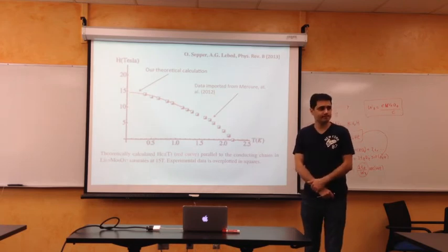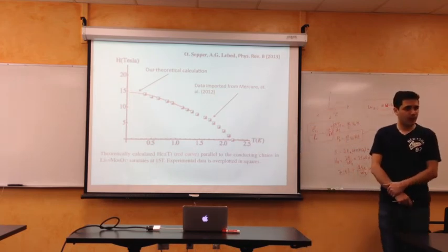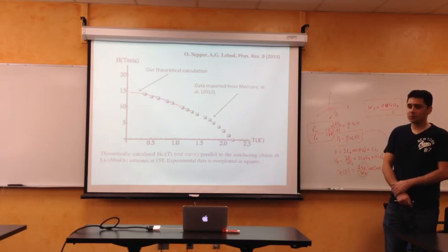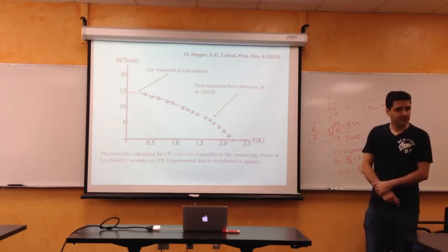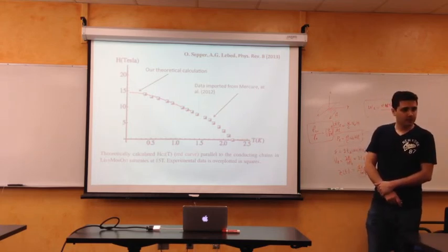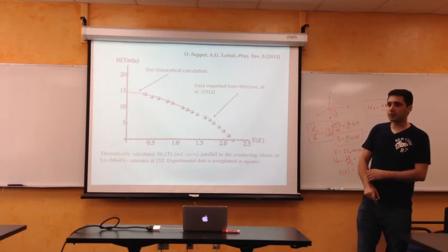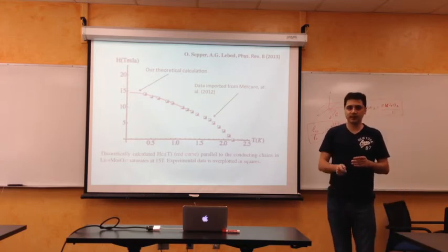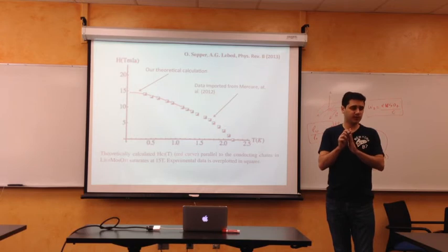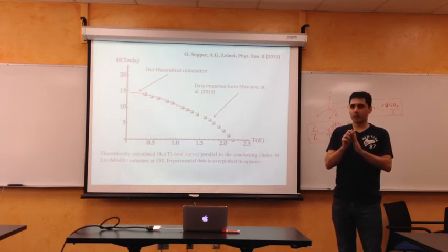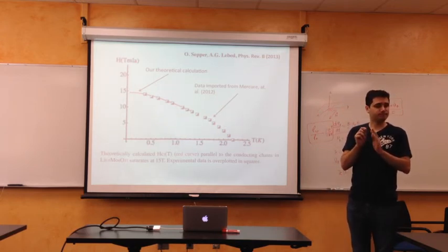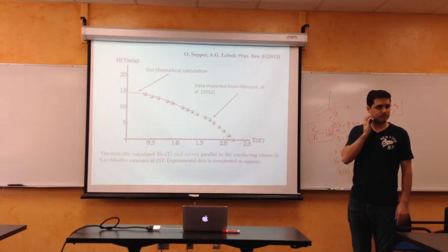So do you assume anything in this model when the pair is triplet? In this model, when you calculate this, do you assume anything when the pair is triplet? There are no assumptions besides the fact that the magnetic field is parallel to the conducting chains, and that's about it. So does that mean HC2 being very high implies something?